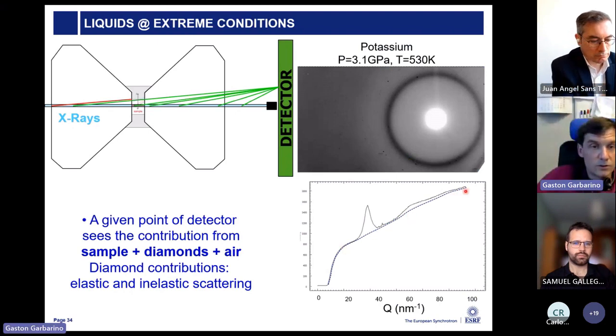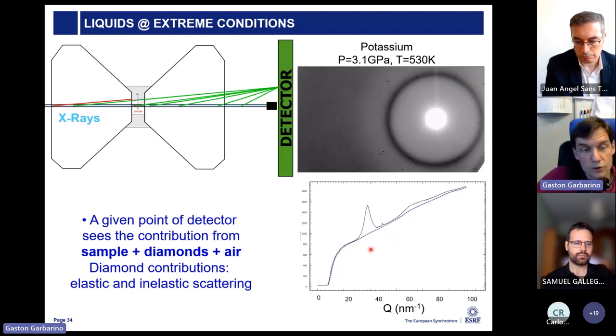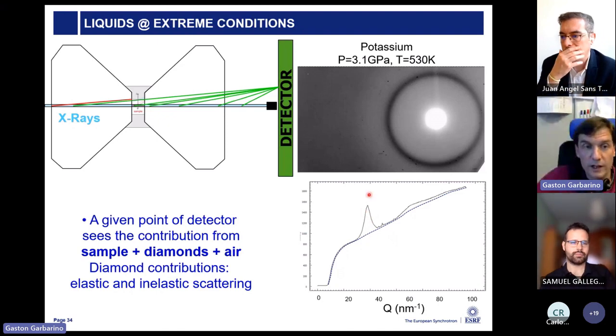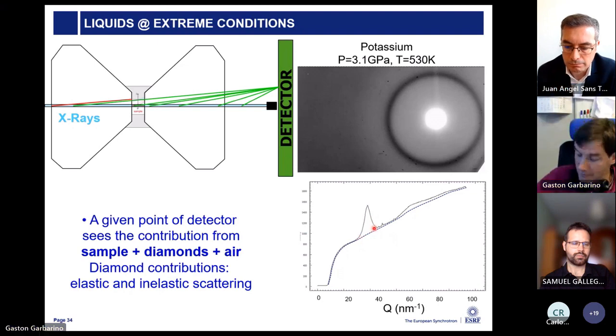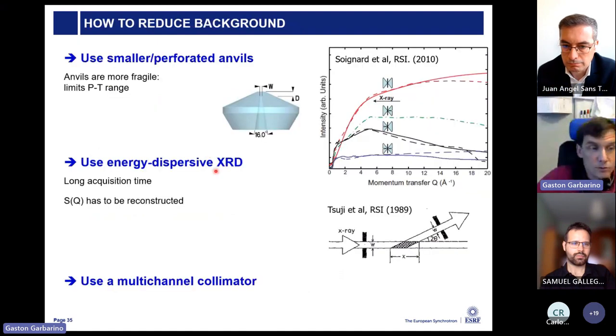And this dotted line here is the signal coming only from the diamonds, okay? And as soon as you put a sample that is very light, for example, in this case potassium, it's not very light, but it's quite light in terms of atomic number, you will see that the contribution of the background is very big compared to what we get from the sample. So this is a big problem, because if you really reduce the atomic numbers, for example, if you want to study hydrogen, the signal will be masked by the background of the diamonds, of the Compton of the diamond.